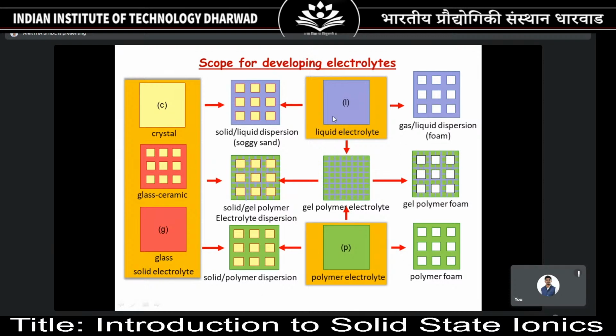Now coming to the liquid electrolyte, we all know that liquid electrolytes are good and they can exhibit high ionic conductivity. But when we use solid electrolytes, our aim is to go nearer to the liquid electrolyte, right? So what researchers have done is add this liquid electrolyte into the polymer electrolyte, and you end up with a gel polymer electrolyte. In between liquid electrolyte and polymer electrolyte, you can end up with gel polymer electrolytes, which are widely used as prototype electrolytes by researchers.